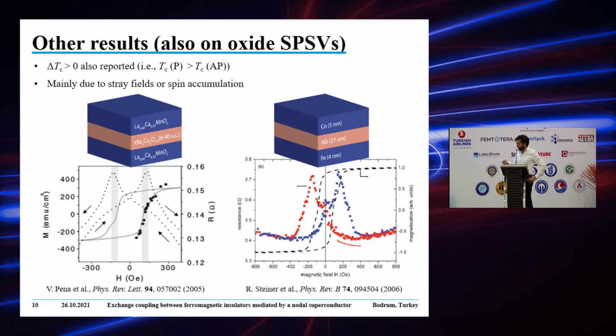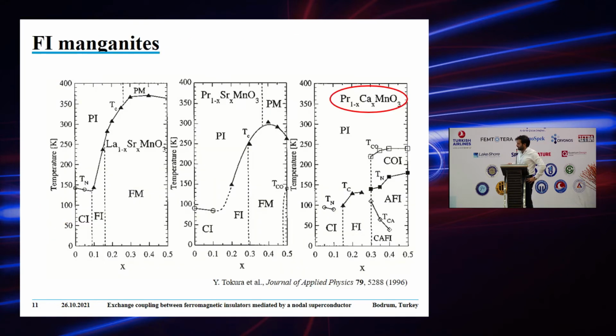So this was the background in the literature. When I started this work, basically the point was, can we do these FI, SFI, so ferromagnetic insulator sandwiching an oxide superconductor using manganites, because manganites give you lots of possibility in terms of choice of the ferromagnetic insulators. So I was looking at this phase diagram, and my choice went on this material, which is praseodymium calcium manganese oxide, for a doping of calcium of 0.2, because in this doping range it's quite stable in this ferromagnetic insulating phase.